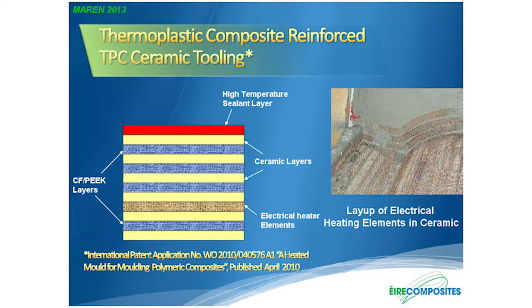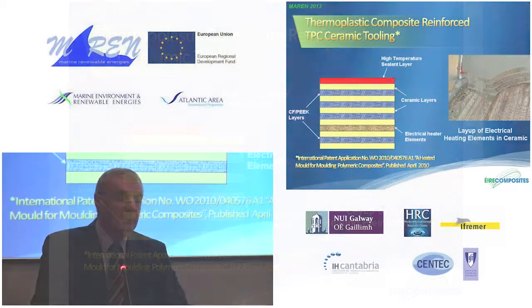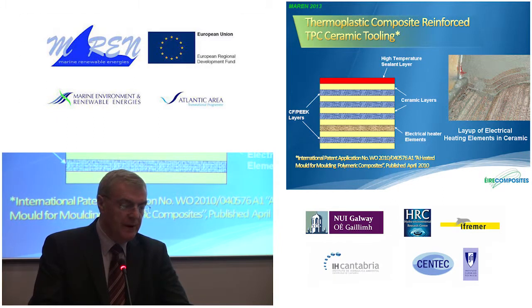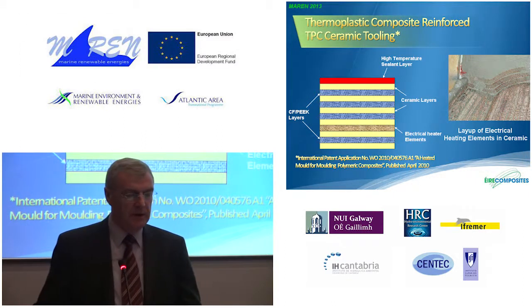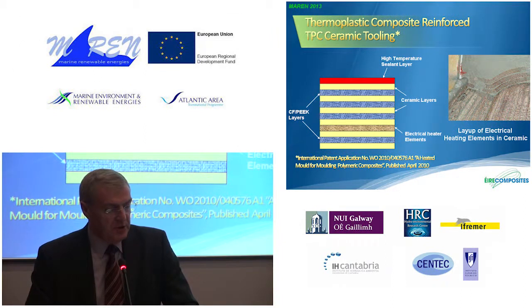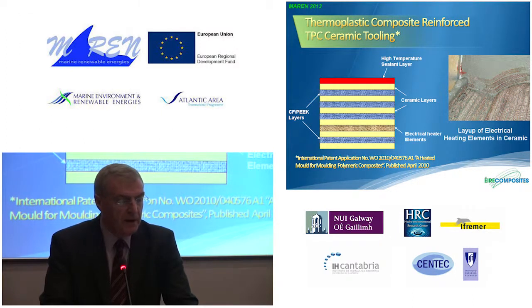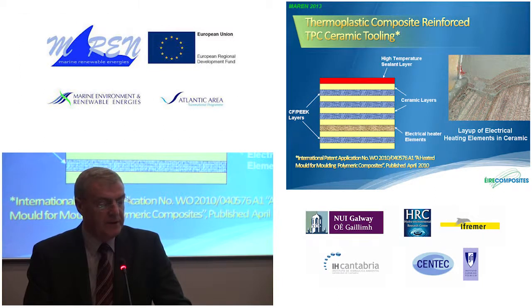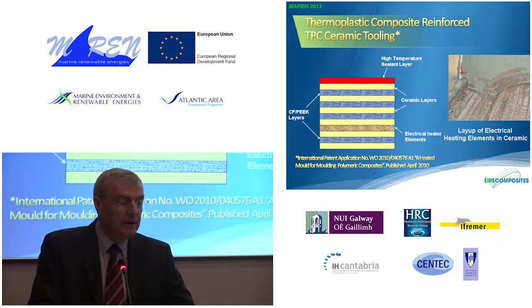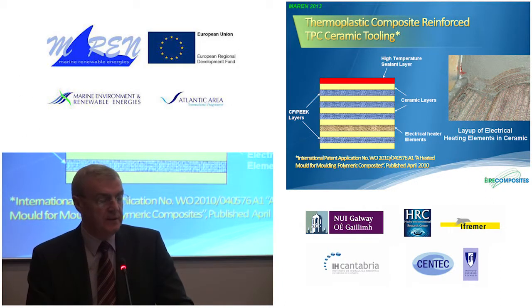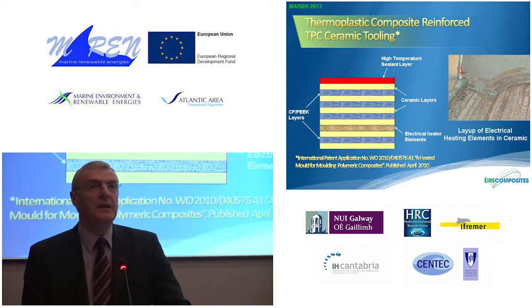This illustrates how a mould is constructed. Once you have a pattern, which can be made from standard tooling materials, whether it's GRP or foam, that has been machined, you lay up the mould in a similar way that you would manufacture other moulds from other materials, where you have alternating layers of ceramics and carbon fibre PEEK. At the B side of the mould, we then lay in the electrical heating elements, and we seal the surface, or the A side of the mould, with a high temperature sealing system that gives you a vacuum tight surface.